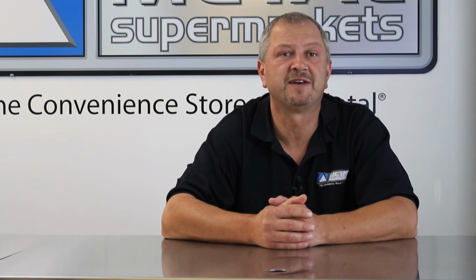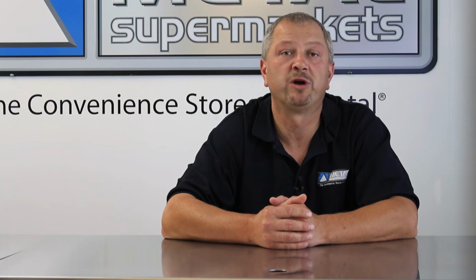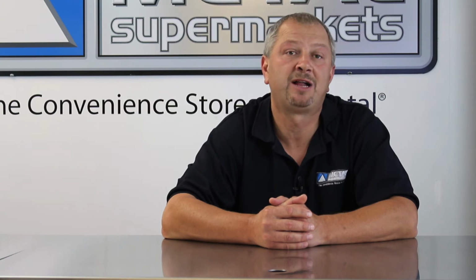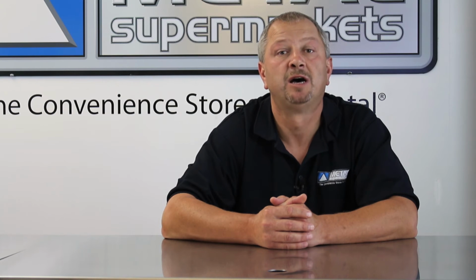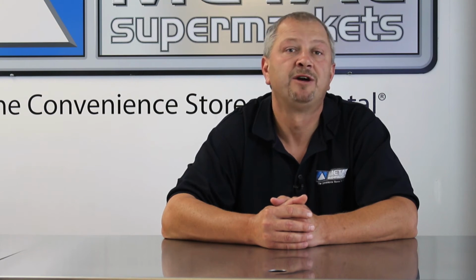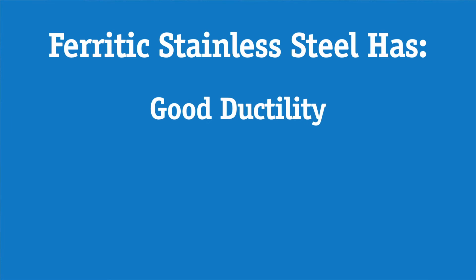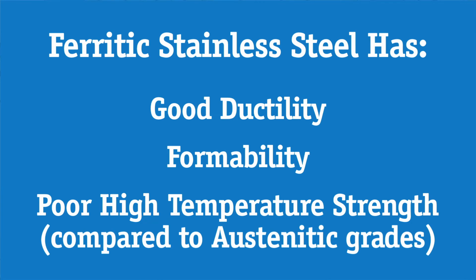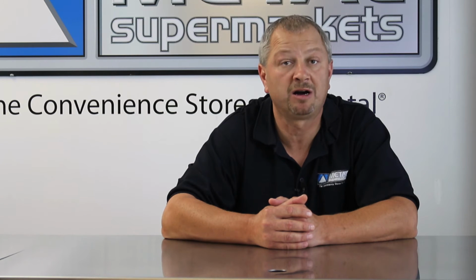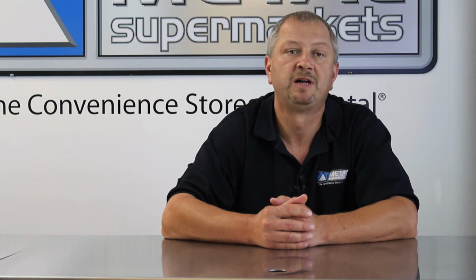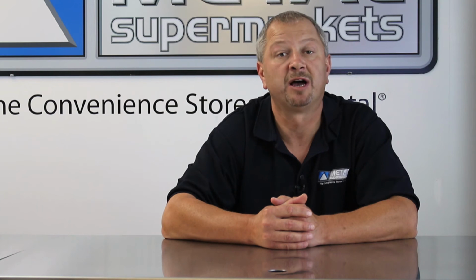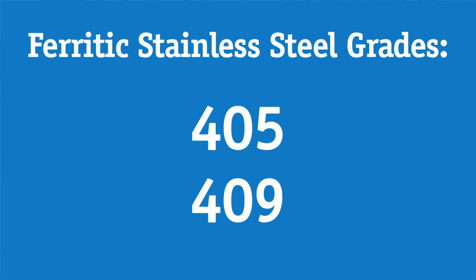Ferritic steels contain trace amounts of nickel, between 12 and 17% chromium, less than 0.1% carbon, and other alloying elements such as molybdenum, aluminum, or titanium. Ferritic steels tend to have good ductility and formability, but relatively poor high temperature strengths when compared to austenitic grades. Ferritic stainless steels are magnetic, but not heat treatable, and often cost less than other stainless steels. Some ferritic grades include 405 and 409.